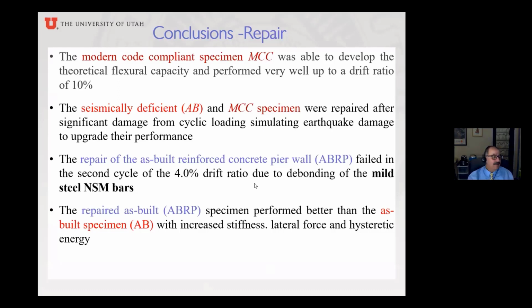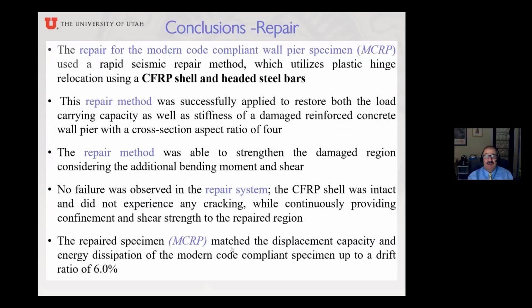So the repair of the as-built one failed in the second cycle of the 4% drift ratio because of debonding of the mild steel near surface mounted bars. I still think the mild steel near surface mounted bars are better than the carbon fiber because they actually give you a little bit more resistance before they break. So the repair of the as-built specimen performed better than the as-built specimen, even though it was repaired, with increased stiffness, lateral force, and hysteretic energy.